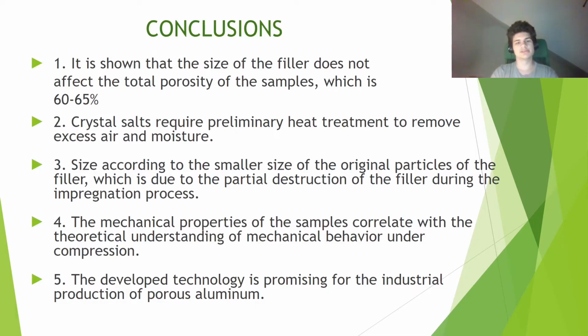So, conclusions. It's shown that the size of the filler doesn't affect the total porosity of samples, which is 60–65%. Crystal salts require preliminary heat treatment to remove excess air and moisture. Pore size corresponds to the smaller size of the original particles of the filler, which is due to the partial destruction of the filler during the impregnation process. The mechanical properties of the samples correlate with the theoretical understanding of mechanical behavior under compression, and the developed technology is promising for the industrial production of porous aluminum.